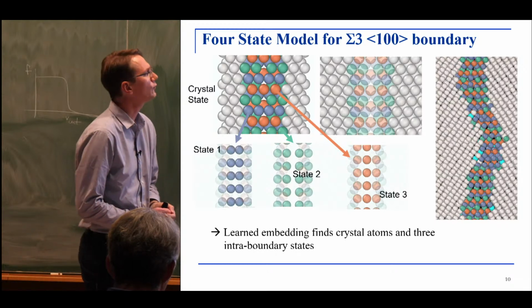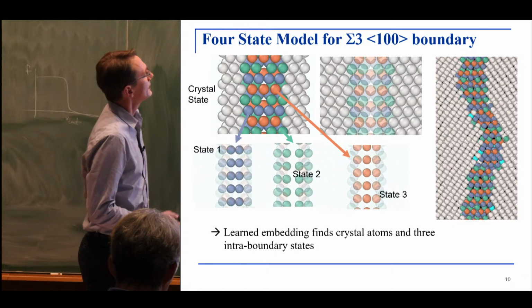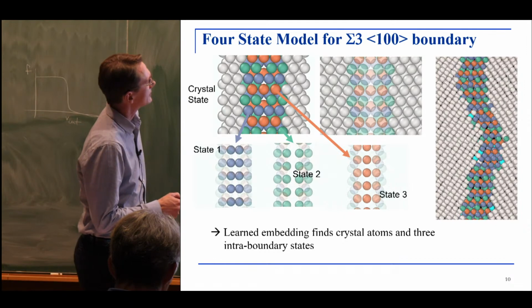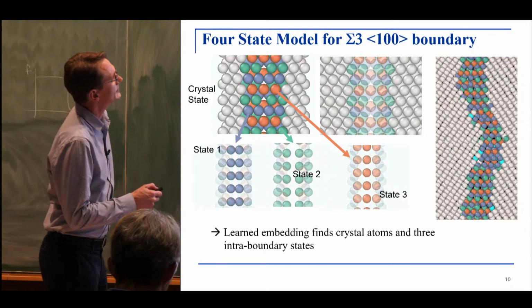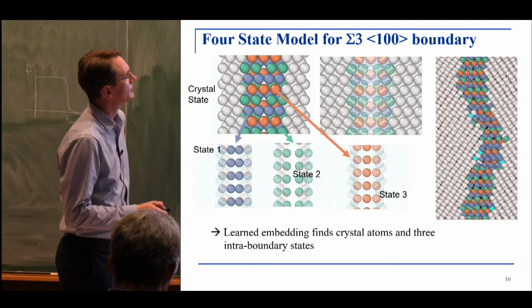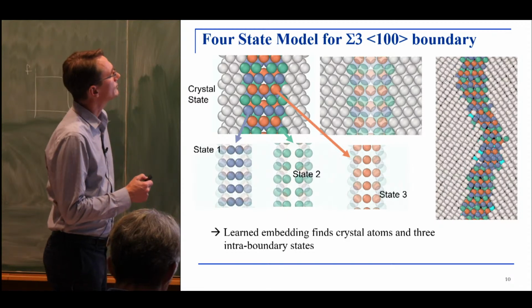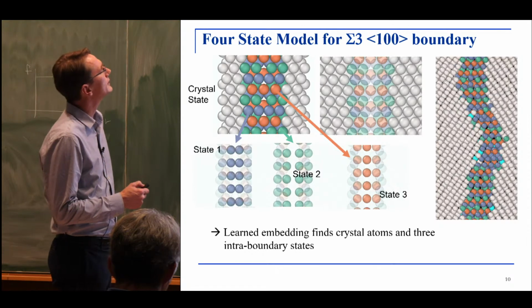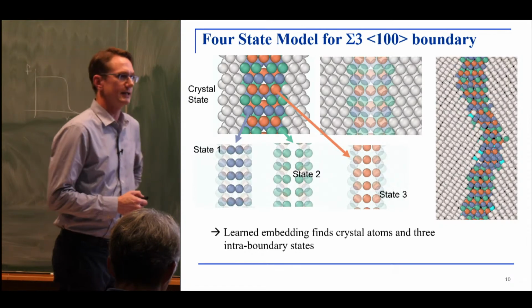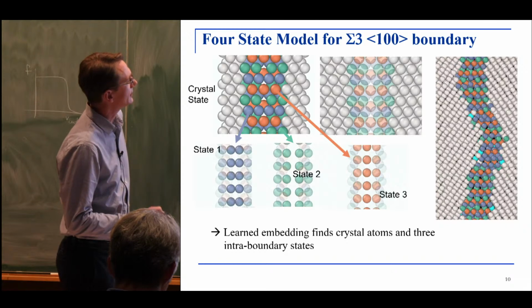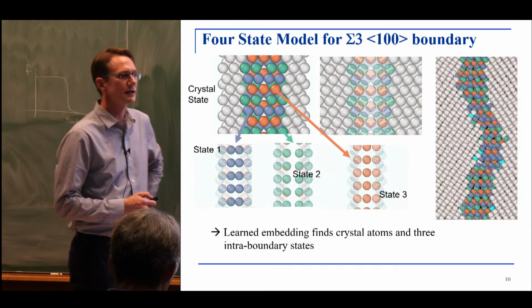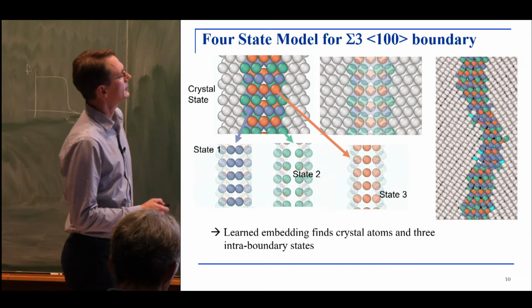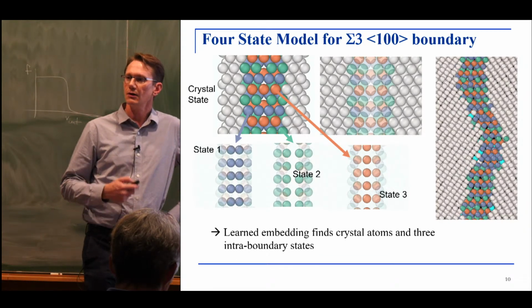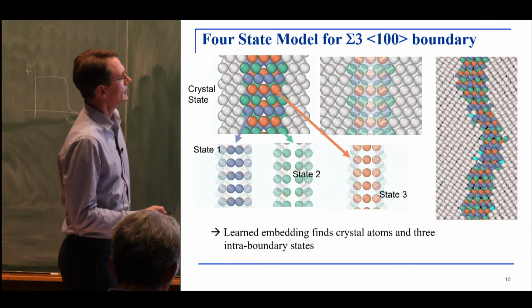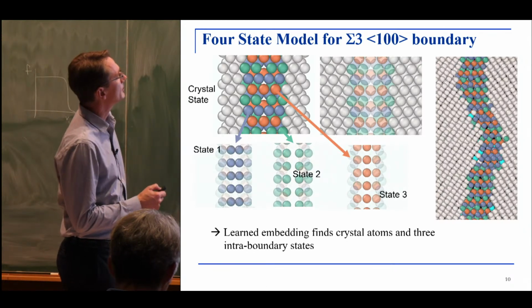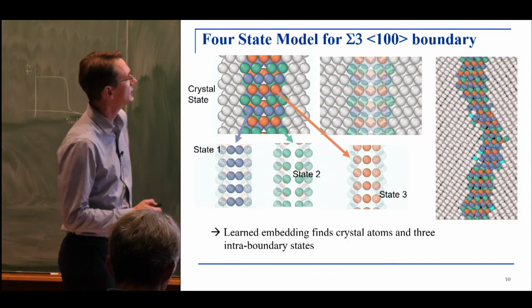Here we are doing a four-state model, and you can see a color assignment on these particles. This is a picture of the thermalized boundary at finite temperature. State 0 in our model turns out to be the atoms in the crystal state, whereas the other states are grain boundary states, the defect states, if you want. Maybe not so surprising, our Markov state model finds the defect, and it identifies several intra-boundary states, which appear to have this layered structure related to the symmetry of the boundary.